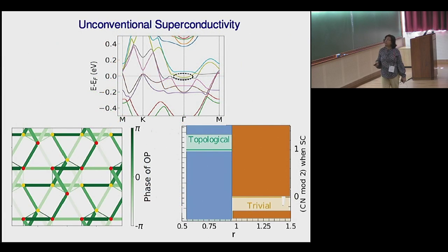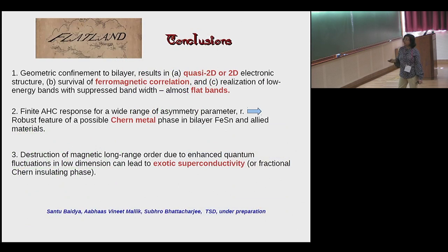And there is also, which is very much work in progress, a possibility of unconventional superconductivity. Since it's a low dimensional material, there can be magnetic fluctuations. So if you have a magnetic fluctuation driven pairing, which was computed by Avash, it shows a very interesting behavior. As you change the R parameter, there is a transition from a trivial superconducting phase to a topological superconducting phase, from a phase hosting an even number of Majorana modes in its vortex core to an odd number of Majorana modes in its vortex core. So, to conclude on this part, my time is up.